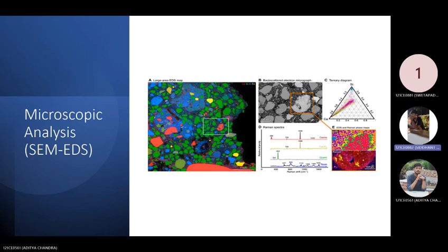As we can see, it is represented by various colors like red, blue, and green, which form ternary diagrams giving us the calcium, silicon, and aluminum compositions. By the wavelength shift of these elements, we can classify them into these colors. And through the ternary diagram, we can see the composition mixture of these samples. As we can see, there is a higher amount of silicon along with calcium, with a lower amount of aluminum in the sample, which is clearly shown in the graphs. Next slide, please.